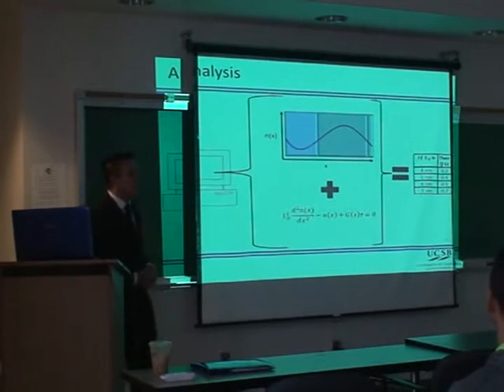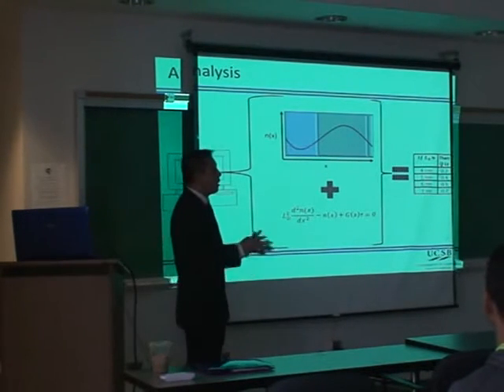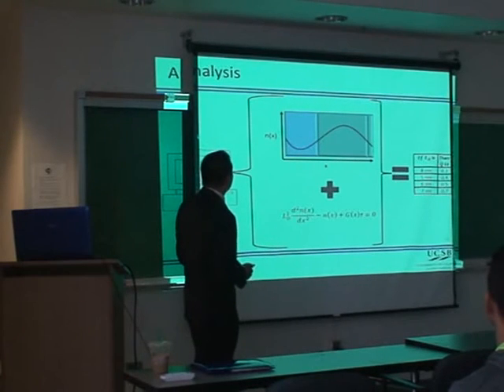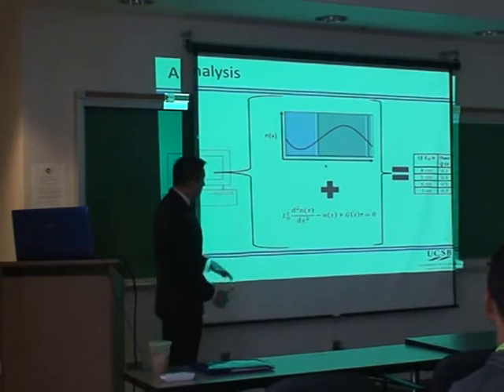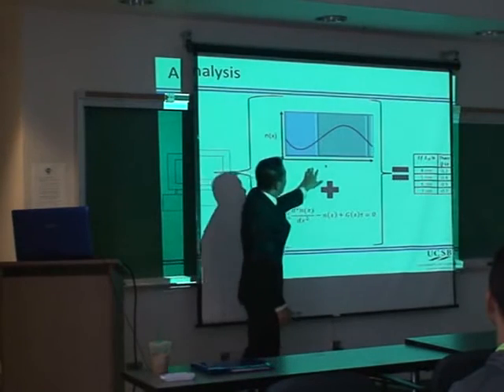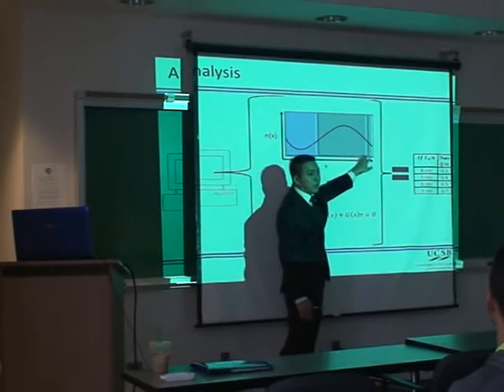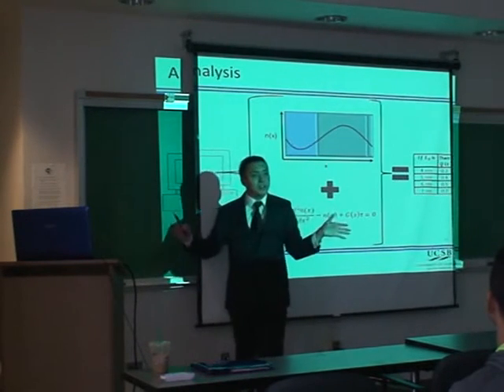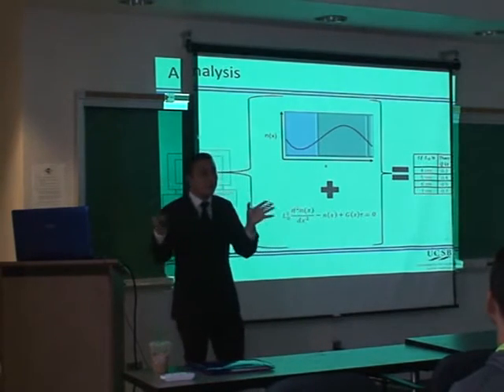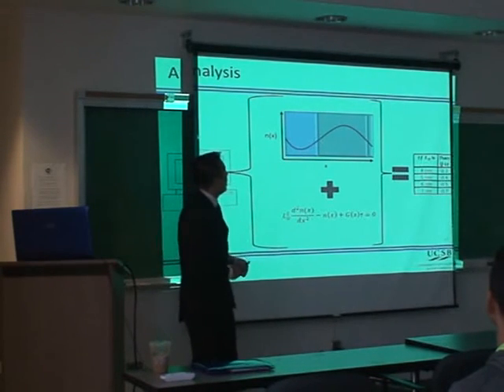So now the question is, how do we connect this measurement with a model to determine what the exciton diffusion length is? Well, what we first have to do is figure out what the exciton density profile is in this film. And actually, it's not homogeneous. You would think that you shine light on this film and excitons are generated equally throughout, but in fact, they're not.